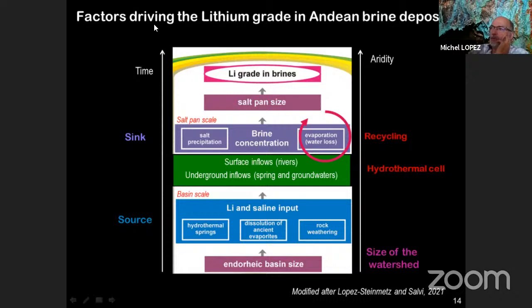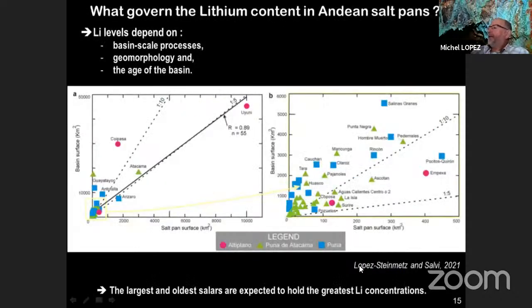The size of the salar is also important. So the time in this process and the aridity are factors that increase the concentration of lithium in the brine. One important thing shown by these authors, Lopez, Steinmetz, and Salvi, is that there is a link between the size of a basin and watershed and the size of the salar itself. So the analysis of different salars in the Andean domain shows that the largest and oldest salars are expected to hold the greatest lithium concentration. The older and larger the salar, the greater the lithium concentration.